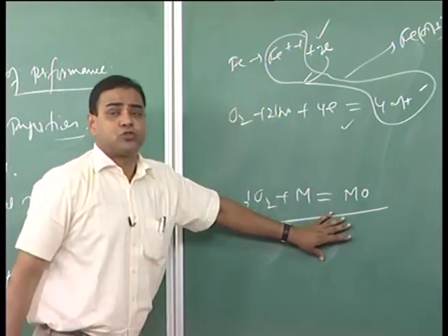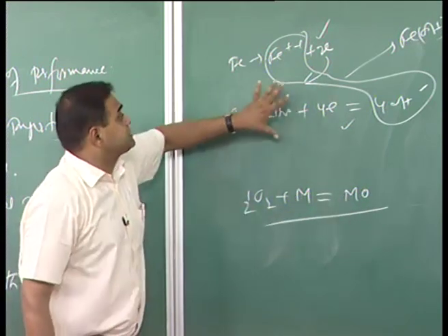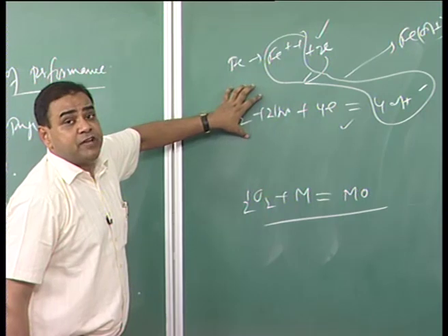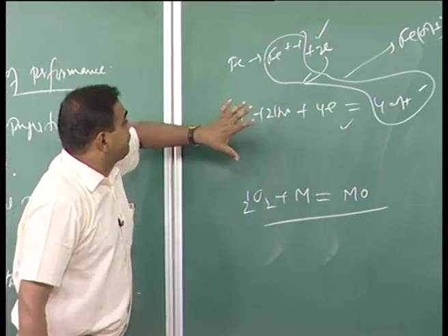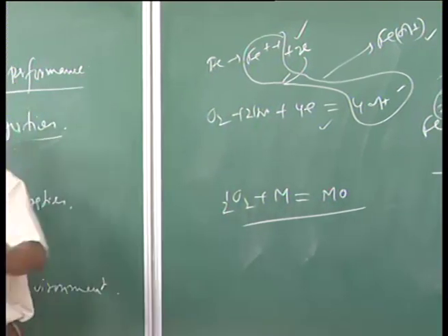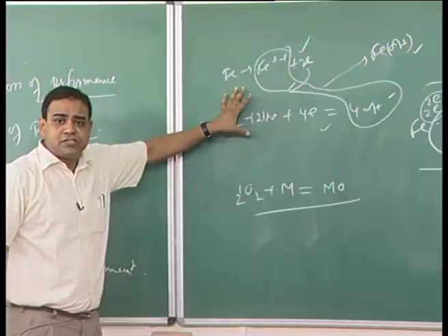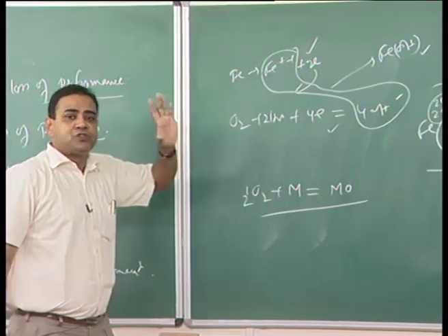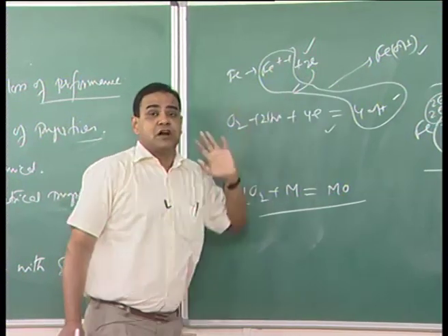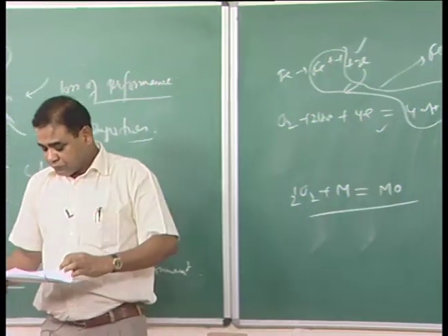This is also a sort of corrosion, but I will come to why it can be considered as corrosion once we understand the electrochemical nature of corrosion. From this it is very clear that there should be one or more anodic reactions and one or multiple cathodic reactions depending on the actual situation, but there should be balance in charges. So no charge should remain free.